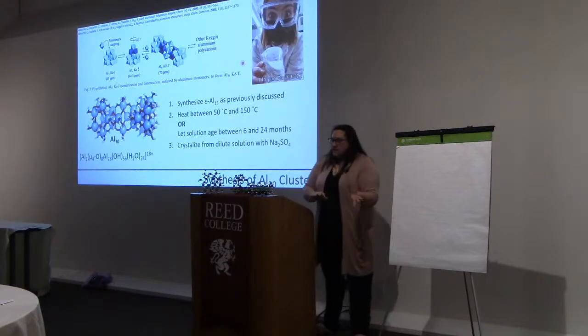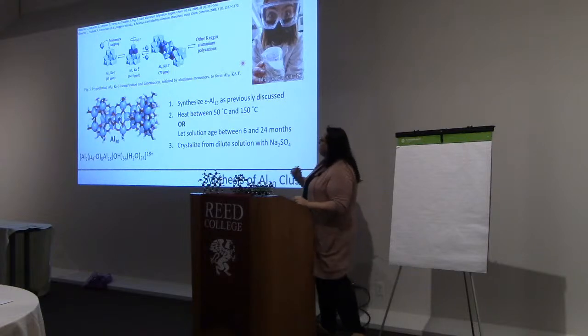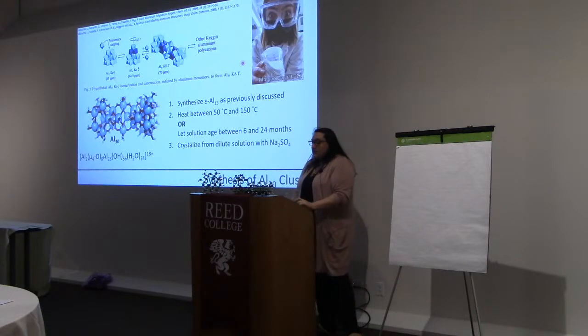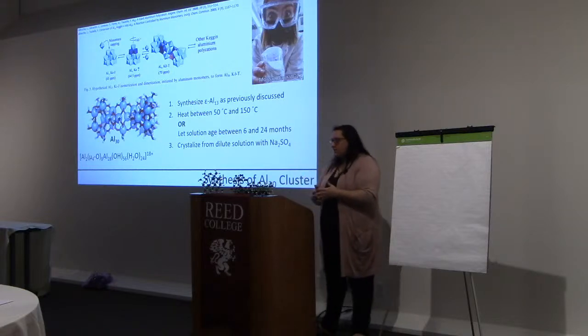The next cluster we synthesized was the aluminum 30. Now this cluster in the literature, the synthesis is that you make the epsilon, as we said on the last slide, and then you either heat it or you just let it sit for a while. Okay, so what they think is that you have this epsilon, you heat it, and you have a rotation of a cap, you get the delta, and then that's in equilibrium with your delta.